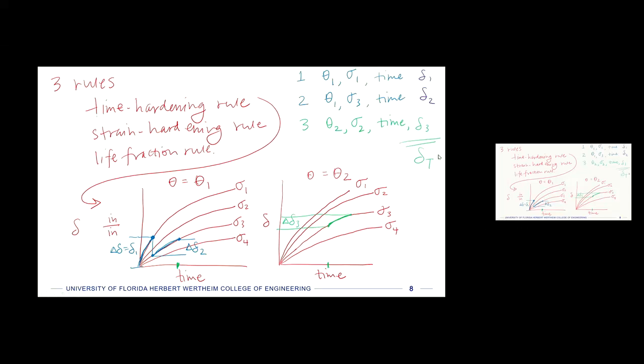That's exactly right. So in this case, we go back and forth, but instead of then adding up the strain levels, we add up the time, right? So we keep the other one constant and then use time as our summation. So in the time hardening rule, just keep it straight. Time hardening rule, time is continuous, add up the changes in strain. Strain hardening rule, we anchor strain across the plots and add up time. And then once that reaches some total design life, then our ratio is 1 and it's met the end of its time based on that summary. Okay.